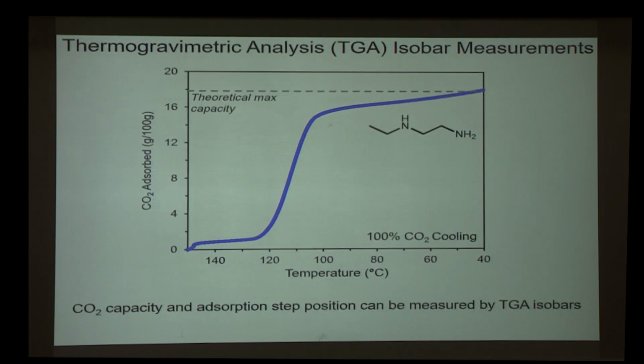Before I show you those results, I need to introduce a slightly different assay, which I'll be showing for the rest of the talk. In this experiment, we expose the sample to a constant pressure of CO2. We start at a high temperature, and we slowly cool. Here, we can still see those sharp adsorption steps, and we get essentially the same information as from the gas sorption isotherms I showed earlier. This is just a more convenient experiment.